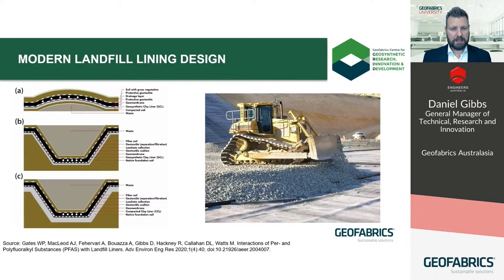There's a body of work being undertaken at present here in Australia, which looks to quantify the effects of PFAS on lining materials such as HDPE geomembranes and GCLs. And this includes not just looking at how these chemicals move through the system from a hydraulic point of view, but also any detrimental effects such as stress cracking, which may occur over time with exposure to PFAS, because it's a surfactant. But based on our current body of knowledge, let's assume that PFAS quantities in landfill leachate are low enough to reduce diffusion through HDPE geomembranes to very low levels. That doesn't let us off the hook, though.